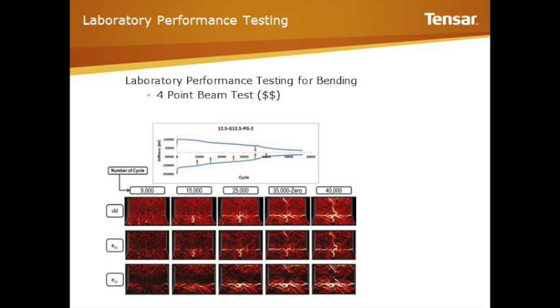But the graphs below it, and I apologize there's so many there, but the interesting thing here is what they did was they used digital imaging capturing technology to evaluate the beam as it is loaded. And those little white marks over there represent strain that constitutes or represents cracking or fracturing. Now, the beautiful thing about this, and remember this is under flexure, is you can see what the performance is at the interlayer and what the performance of the crack is going through it. Well, when you look at the specimen after the test is completed, you'd be amazed to see that there are no cracks. So you actually go there and you go, well, how is it possible we can see fracture during displacement, but you don't see fracture post the test?